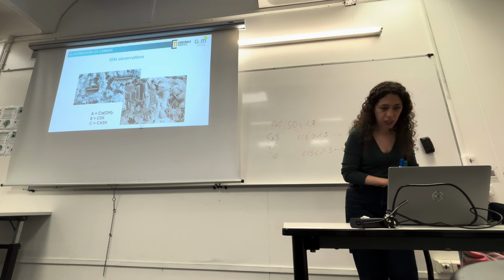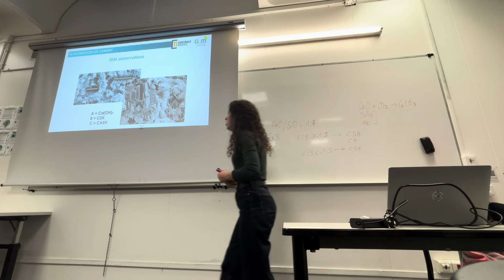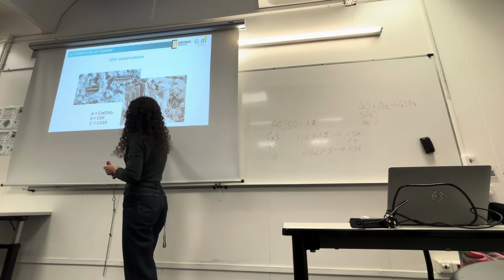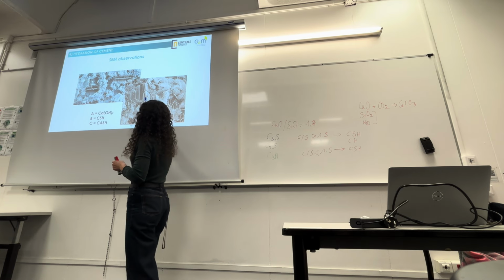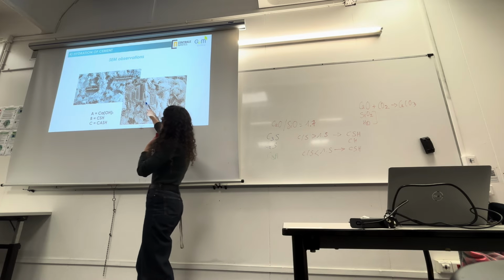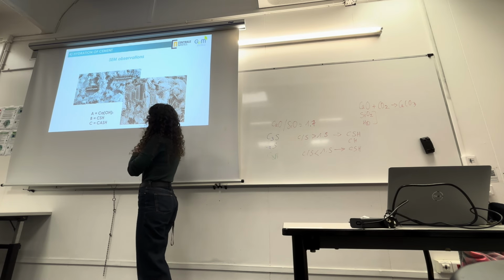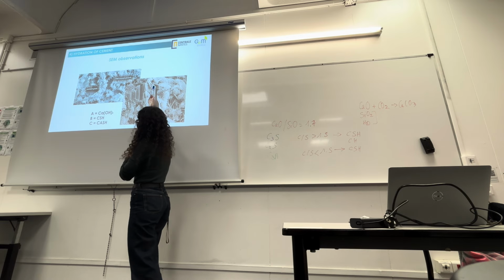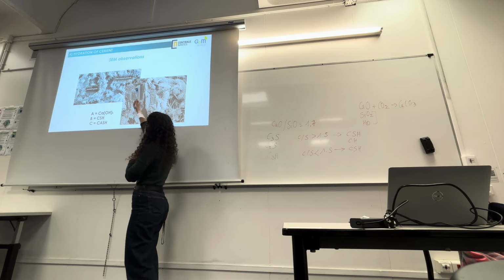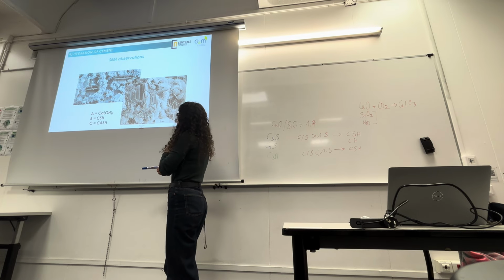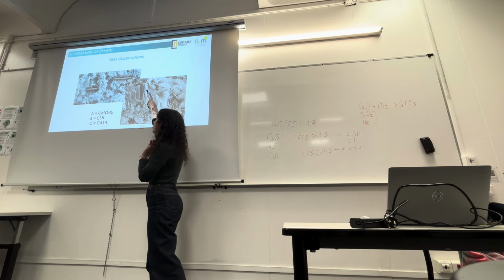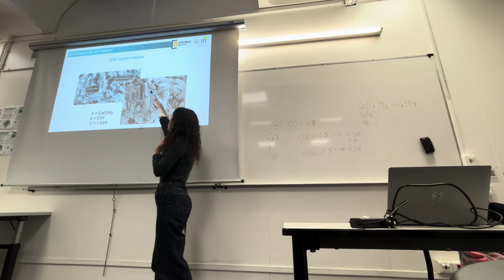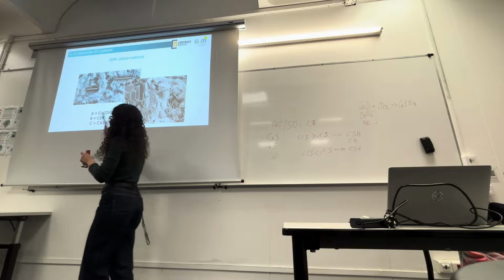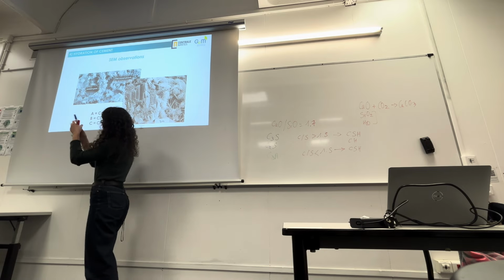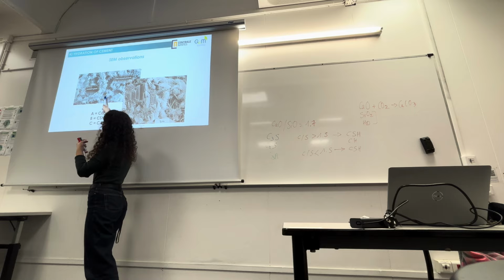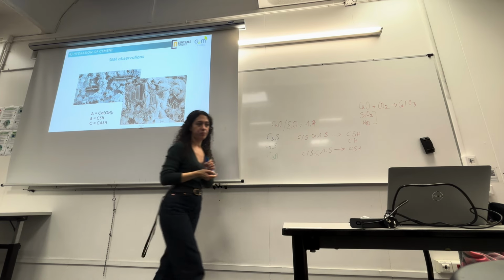So, okay, you have a different observation. You have the CSH and the portlandite that is well crystalline inside the CSH, and then they say this is CASH, but I'm not sure actually. I've never observed CASH by STEM. I don't know if it's like this. But here you see the CSH, amorphous, growing around the cement grain.